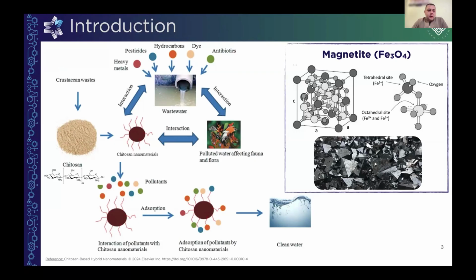so those are always interacting with different toxicants, and this chitosan is also used in our daily life. We can use it as an additive to food, and it seems to be a very good material to use because it can be easily obtained from our life and from crustacean wastes. Also, for a better collection of it, we decided to add specific magnetic properties by connecting magnetite. So then we can collect the used sorbent from the environment just using a magnet.